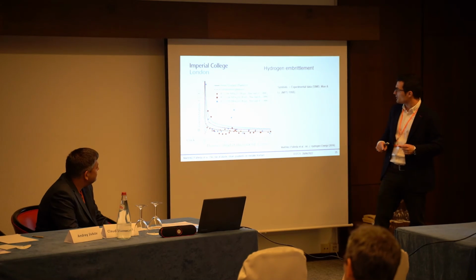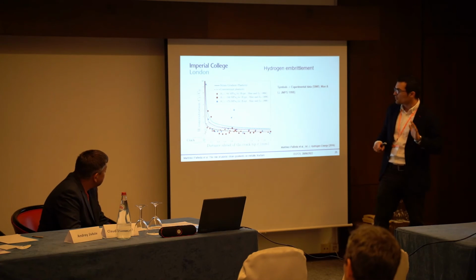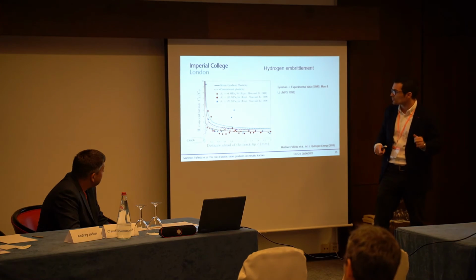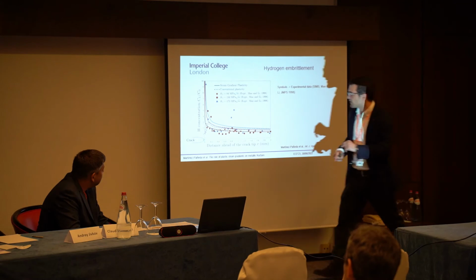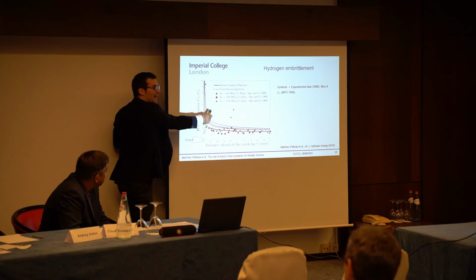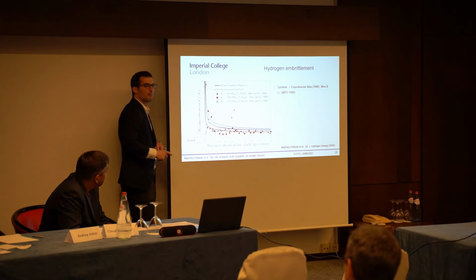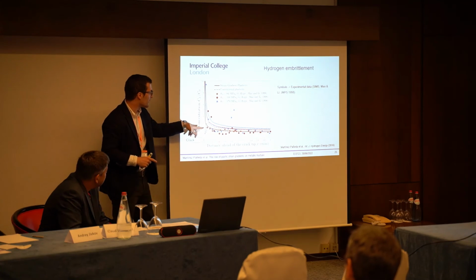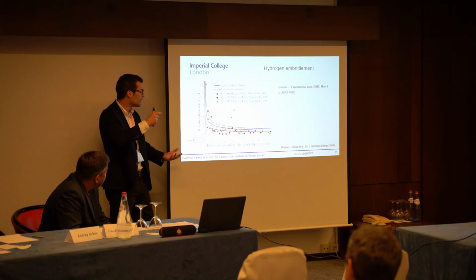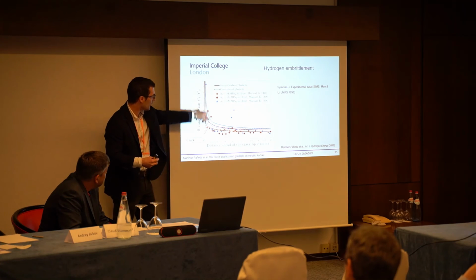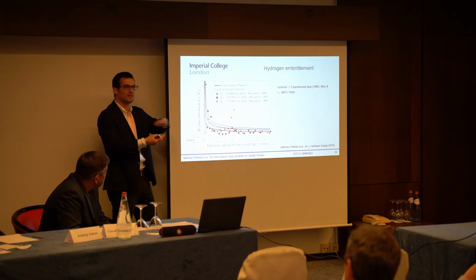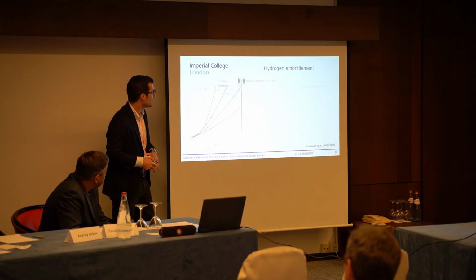And in fact, this is one of the examples. So these are some SIMS measurements of hydrogen content ahead of the crack tip. And you can see that only by using strain gradient plasticity are we able to capture two things that you see in the experiments. One, that the hydrogen content increases ahead of the crack tip. As you approach the crack tip, you can see it's very high hydrogen content, nowhere near the conventional plasticity prediction. And the other one is that as you increase your mechanical load, you get higher hydrogen content. You don't get that anymore in conventional plasticity as your crack tip stresses are constant.